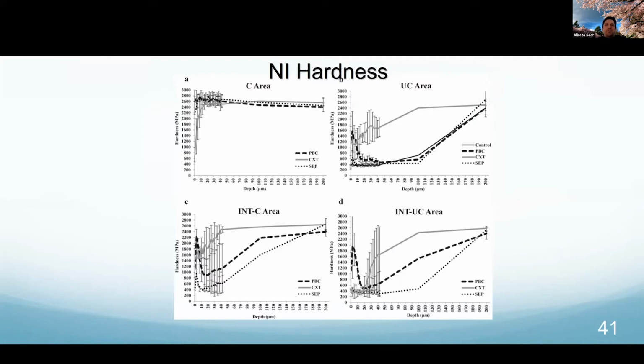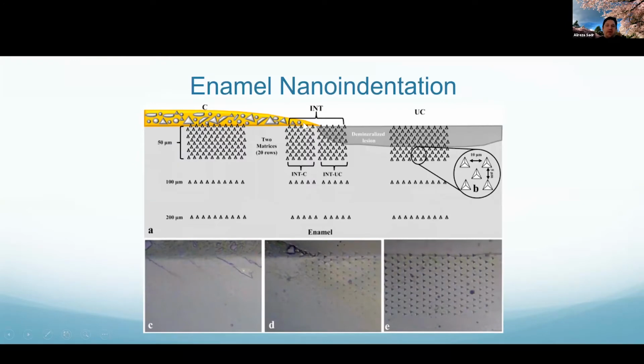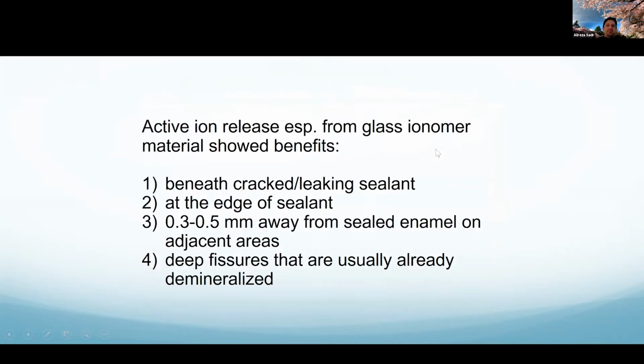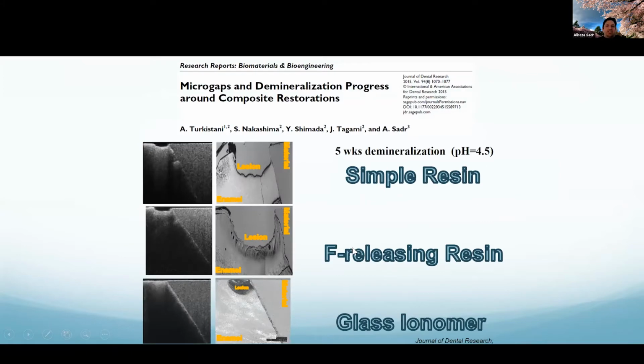So what we found here, I'm not going to get into this graph. What we found here is that there is advantage of the glass ionomer-based sealant when compared to resin-based sealant in terms of the intermediate area and also in terms of the hardness of the demineralized area around our sealant. Okay, so yeah, 0.3 to 0.5 millimeter away from the sealed enamel in adjacent areas.